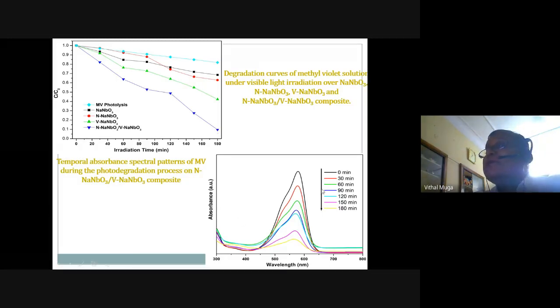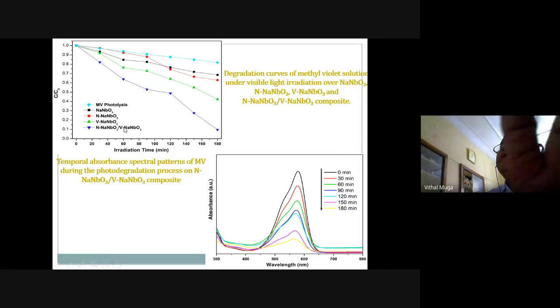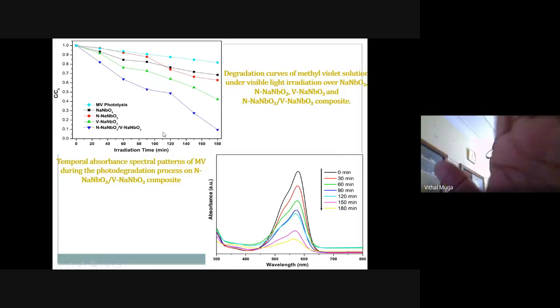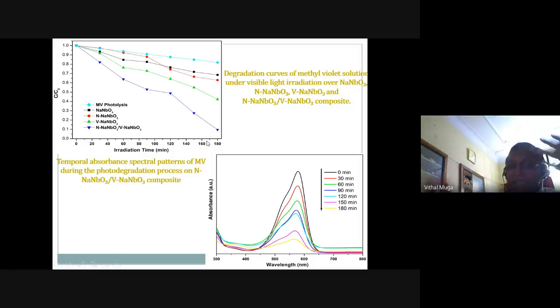Now you look at the methyl violet spectrum. At 0 minutes, this is the optical density, but as the time of irradiation increases, you look at this, it has gone to about 10% of the original value only. That means the composite is much better than the individual two components. Now this is another method of tailoring or increasing the photoactivity of a material.